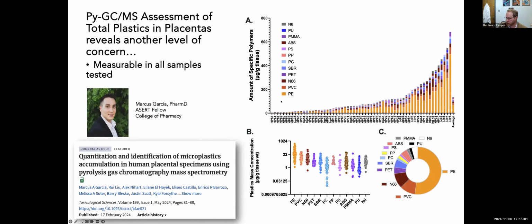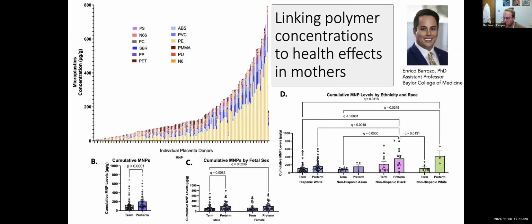Each of the different colors here is representing a different polymer. So polyethylene, polyvinyl chloride, nylon, PET, styrene butadiene rubber, etc. And you can see that by and large, polyethylene is the dominant polymer that we see, followed by typically polyvinyl chloride and nylon and PET. Typically, we see more polypropylene as well, and I'll show you more from different organs where that's more prevalent.